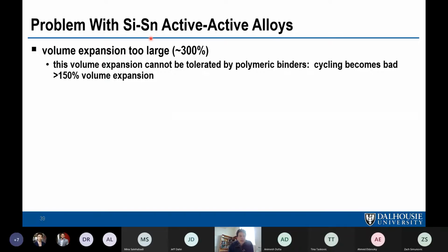But still, one problem with these alloys, if you make them fully amorphous, is their volume expansion is just too large. And in the case of silicon tin, again, it's about 300% volume expansion. And our experience at 3M was that if the volume expansion became larger than 150%, composite electrode coating could not tolerate it, and you get bad cycling no matter what you did. So we tried to limit the volume expansion to less than 150%, and more typically about 100% volume expansion.